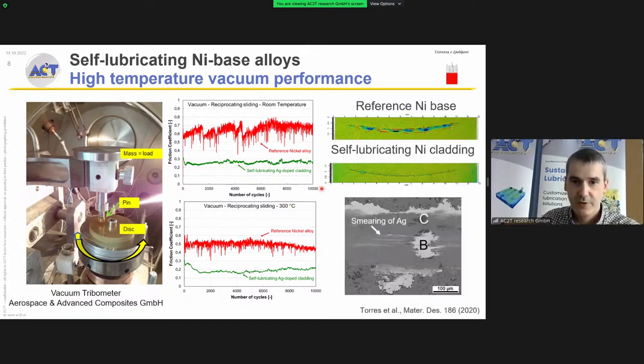And in this case, what we can observe also is that not only the friction is much better, but also the wear is much better. For the reference nickel-based cladding, we have severe plastic deformation and an irregular wear track, and then we have the self-lubricating nickel cladding. Friction is very, very small, with a very homogeneous wear scar, very narrow, very thin. And we can see here in the scanning electron microscopy image how this smearing of silver, supported by thermal softening at 300 degrees, aids in controlling friction at these temperatures.